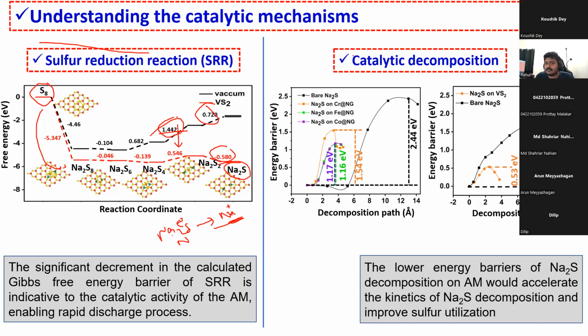But for that, during the charging process, we actually calculated the catalytic decomposition or the NEB, based on nudged elastic band calculation. We calculated the bond breaking of sodium sulfur, and we actually calculated how the sodium ion will be diffusing. So when we calculated the bond breaking, we found that for the pristine Na2S, if you have a simple Na2S without any catalyst, that bond breaking will happen at 2.44 electron volt. It's very high actually. But when we put that on a single atom catalyst, you can see that the bond can be easily broken and sodium can be easily gone. How you can see that? From a very low energy barrier. It's like the energy barrier is only 1.54. You just have to cross this energy barrier to make this reaction happen.